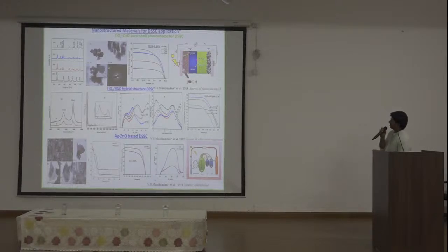But in this counter electrode part, we have worked on the electrode and electrolyte interface, meaning counter electrode and electrolyte. Here the semicircle is reducing after inclusion of the RGO, so it improves the charge transportation. So the RGO is not only providing more dye molecule absorption on the surface, but it is also improving the charge transport resistance.